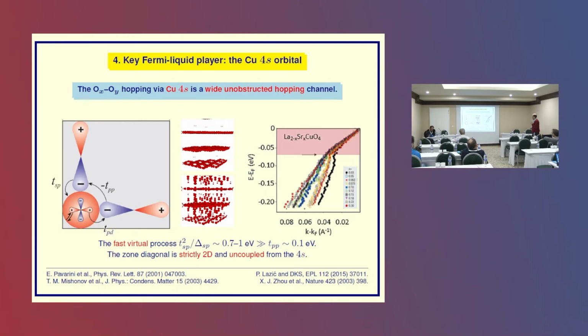Net effect is that it only has the t_pp hopping to use. And look at this. This is one figure which has been repeated many times. You have the same slope of the diagonal electron independent of doping. And the reason is that they have like a mouse hole to go around everything, which is small. And now when you go to a higher energy scale, then you start bumping into the d orbital. You cannot use the s orbital here because you don't see it in wave function space. The wave function is orthogonal to the s orbital.